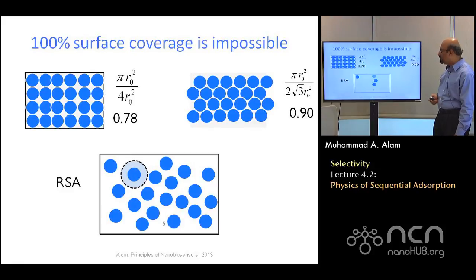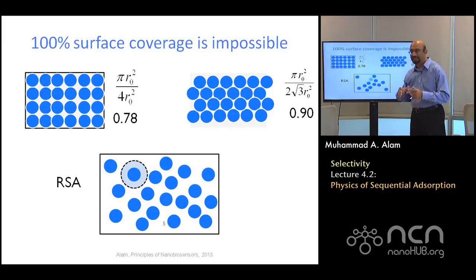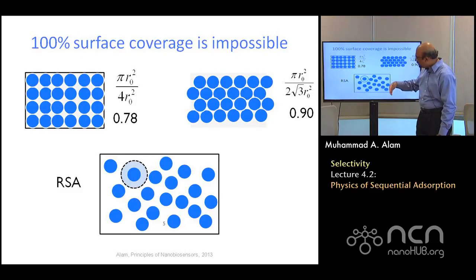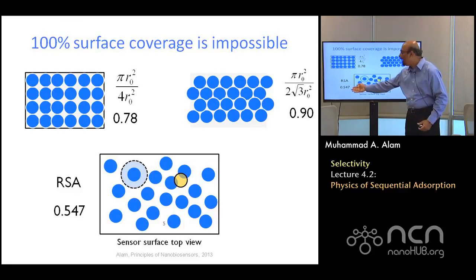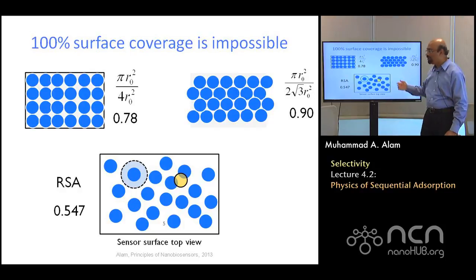It turns out that if you throw things one at a time, like a child putting a penny on a two-dimensional surface, and if they get stuck, let's say it's a glue, then if you try to bring any more, you cannot put them in because they don't fit. And eventually, at steady state, you will only have slightly more than half filled.